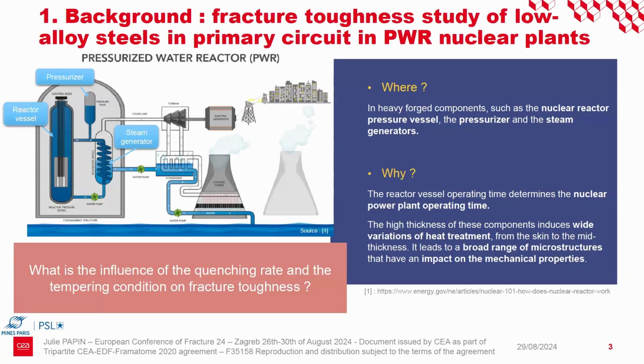So low alloy steels can be found in the primary circuits of pressurized water reactor nuclear plants, in particular in heavy forged components such as the reactor vessel, the pressurizer, and the steam generators. We study the fracture toughness of low alloy steel because the reactor vessel operating time determines the nuclear power plant operating time. Furthermore, the high thickness of these components induces wide variations of heat treatments from the skin to the mid-thickness, and it leads to a broad range of microstructures that have an impact on the mechanical properties. One of the main industrial challenges is to guarantee the integrity of the vessel, even in accidental cases. It is why we study the influence of quenching rate and the tempering condition on fracture toughness.